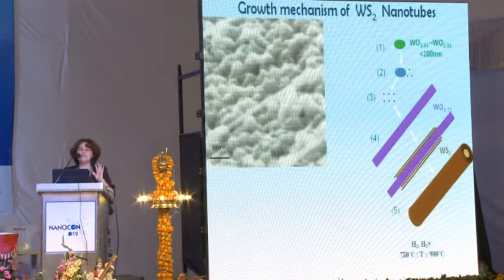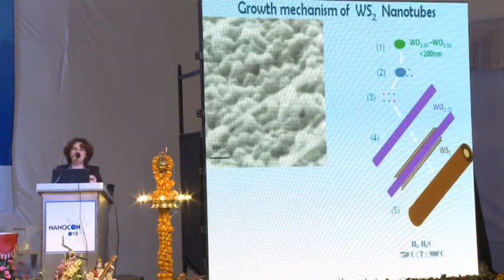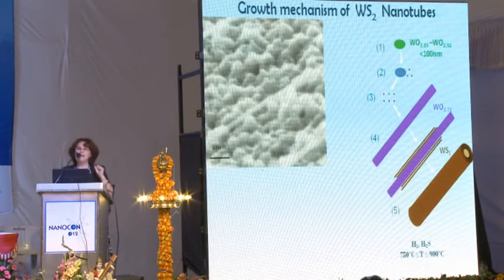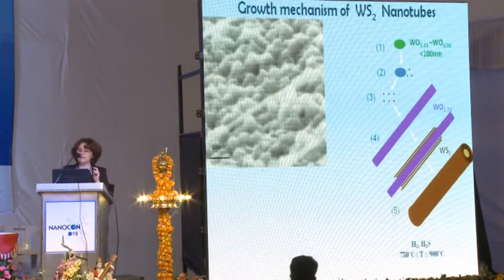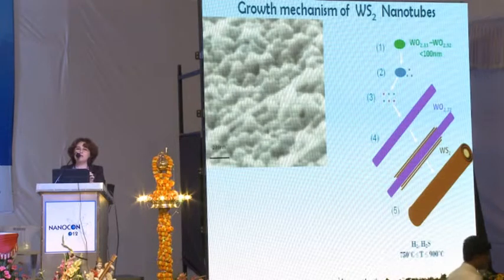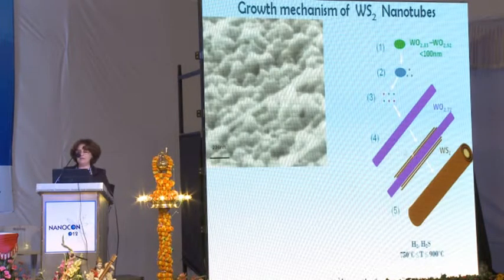The synthesis is not simple. It's at high temperature, but by working hard, we succeeded in getting good results. We start from small nanoparticles of tungsten suboxide. Here you see in parallel a scheme and also real pictures from SEM and TEM. This is the starting material, a mixture of suboxide nanoparticles, and this is how it looks in the SEM picture.